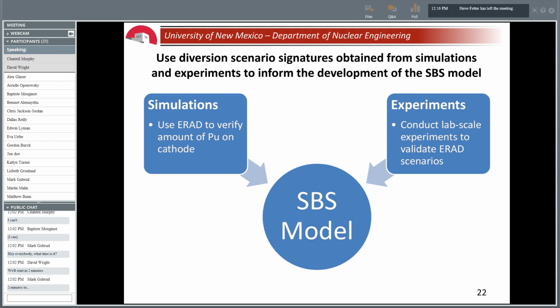Examining these assumptions in simulations and experiments helps build the overall SBS model by providing diversion scenario signatures for a variety of off-normal events, to help identify early their safeguards significance. Simulations for the Electrorefiner are being carried out with a one-dimensional electrochemical transport code called ERAD, or Enhanced Reduction with Anodic Dissolution. ERAD computes the output: the current densities, electrode potentials, and concentrations of elements at various locations in the system.